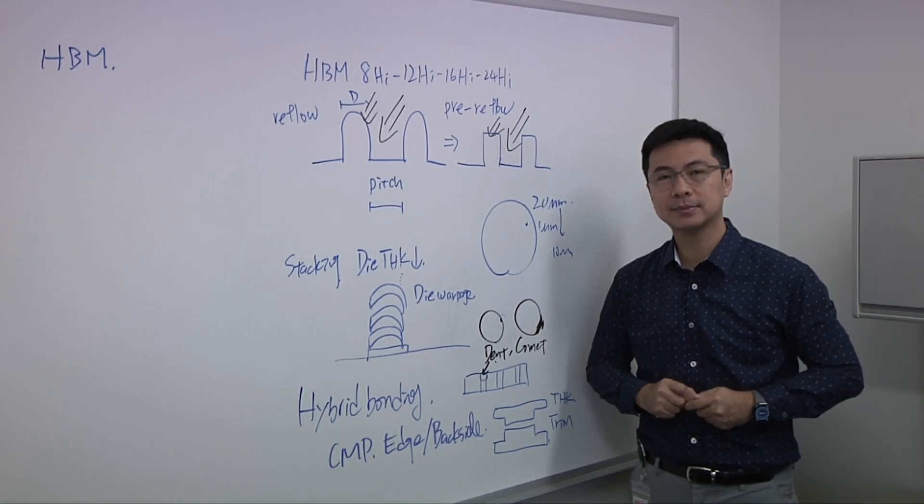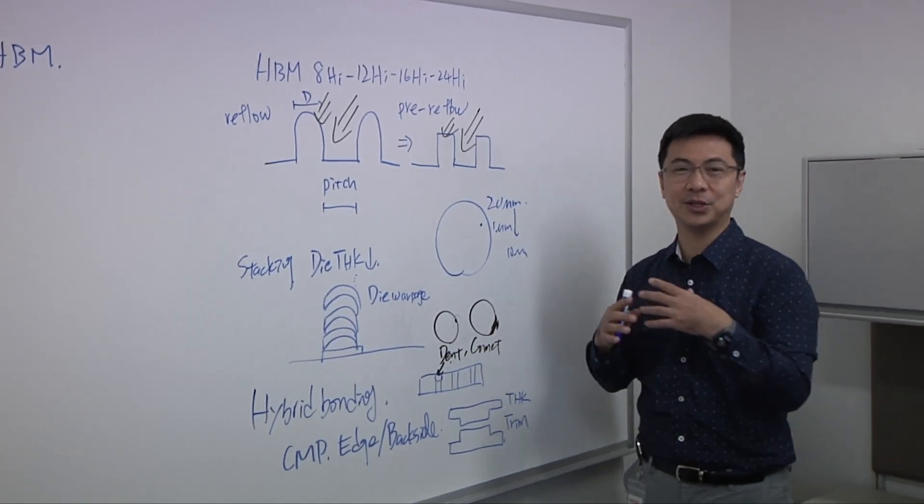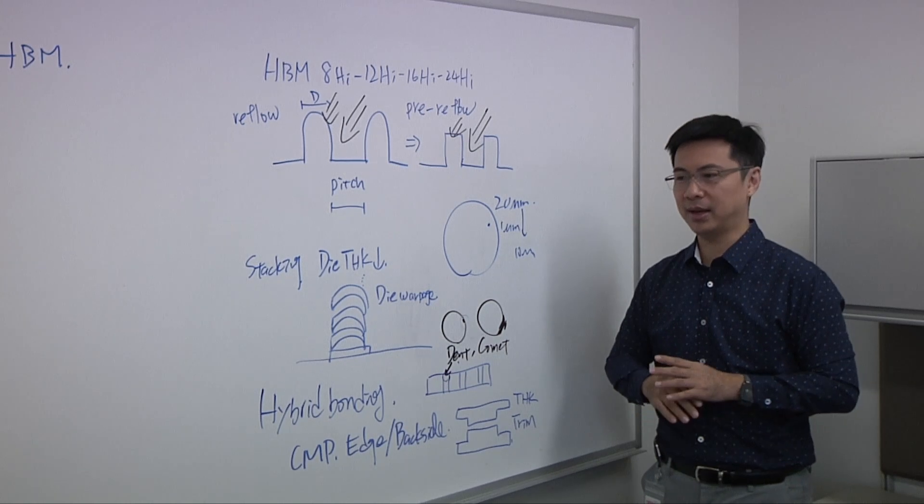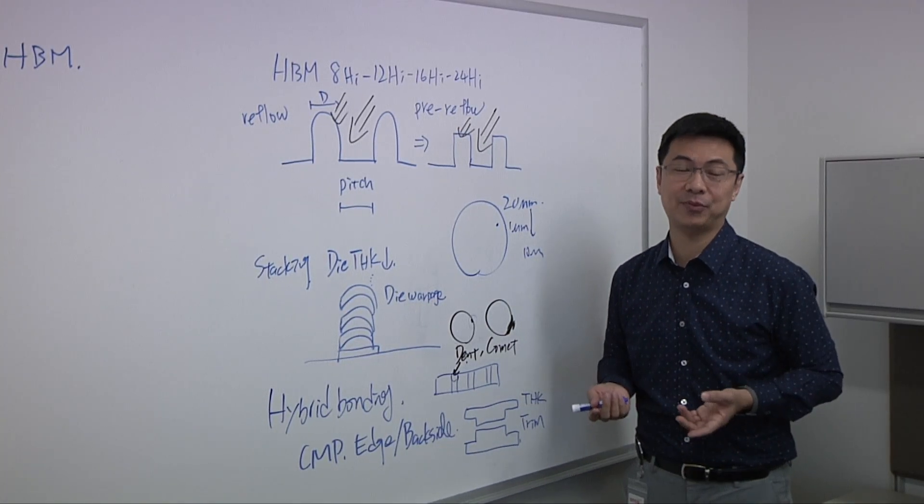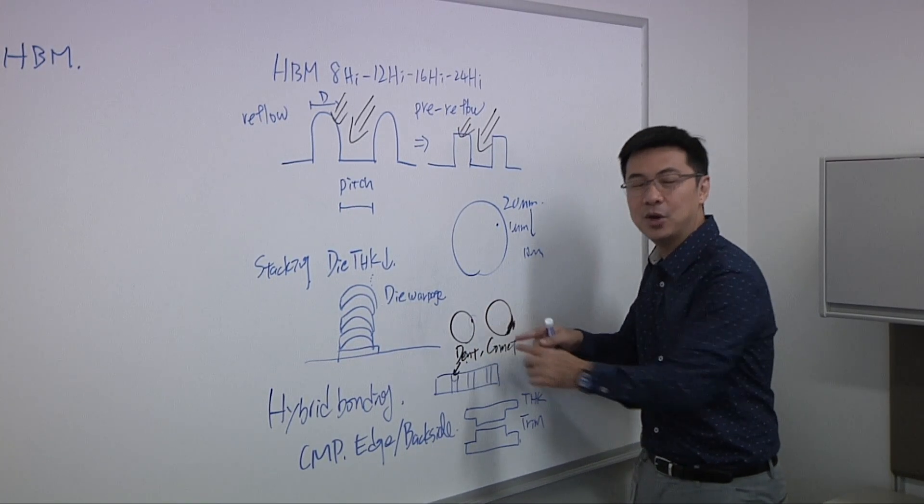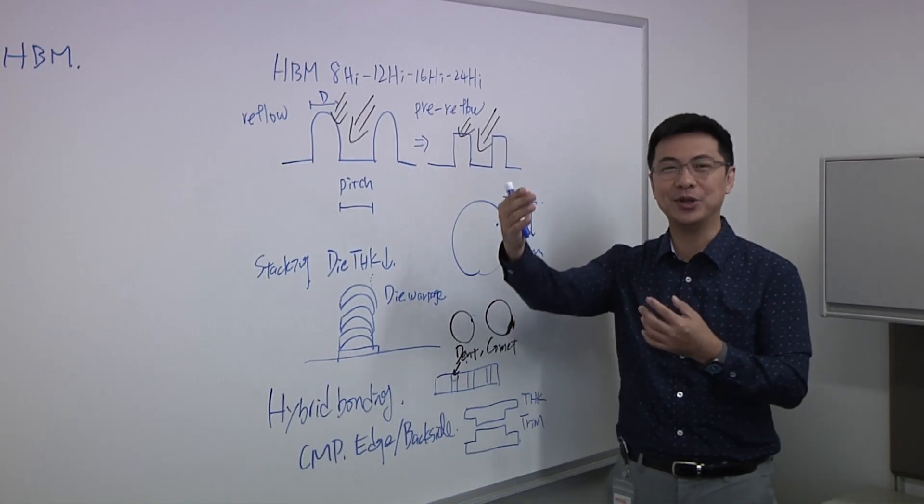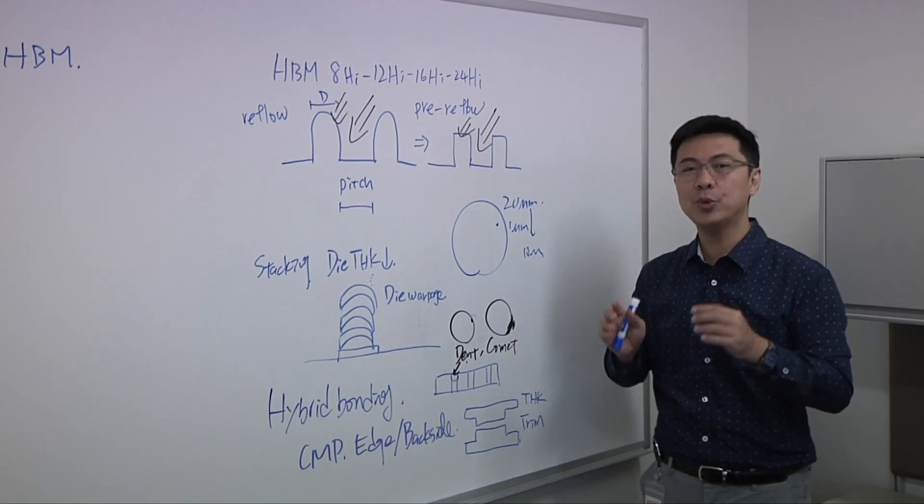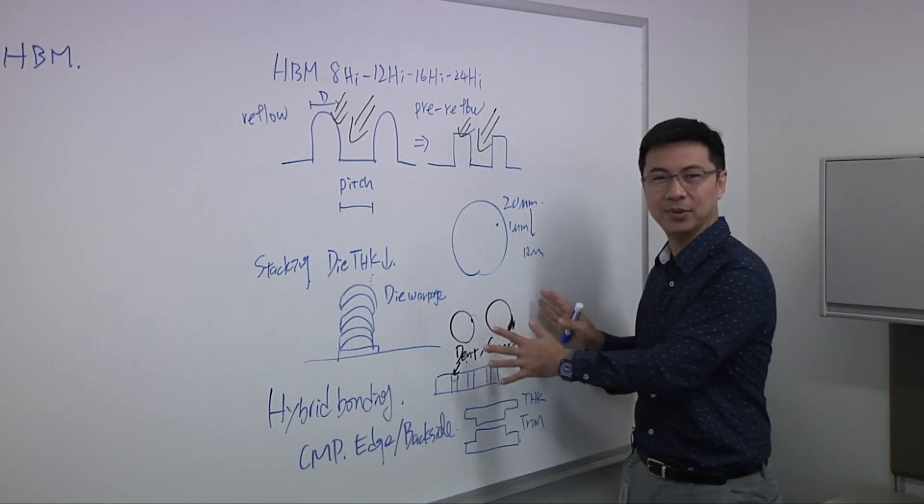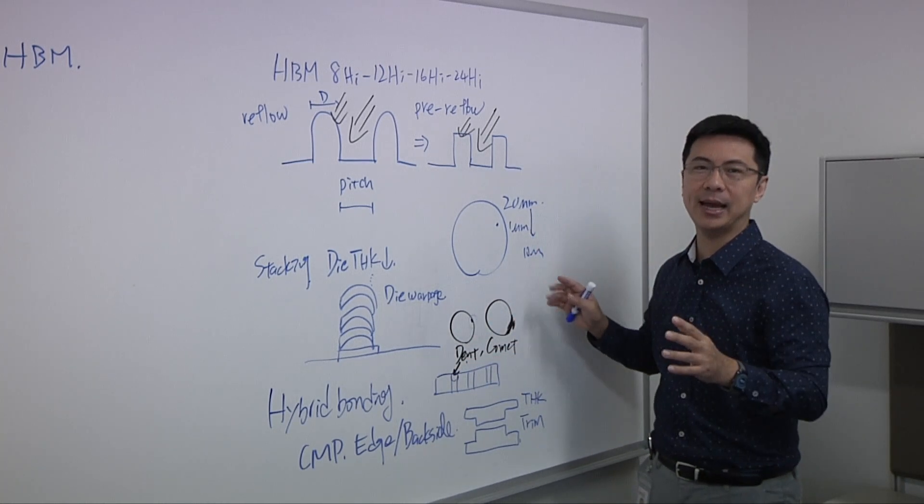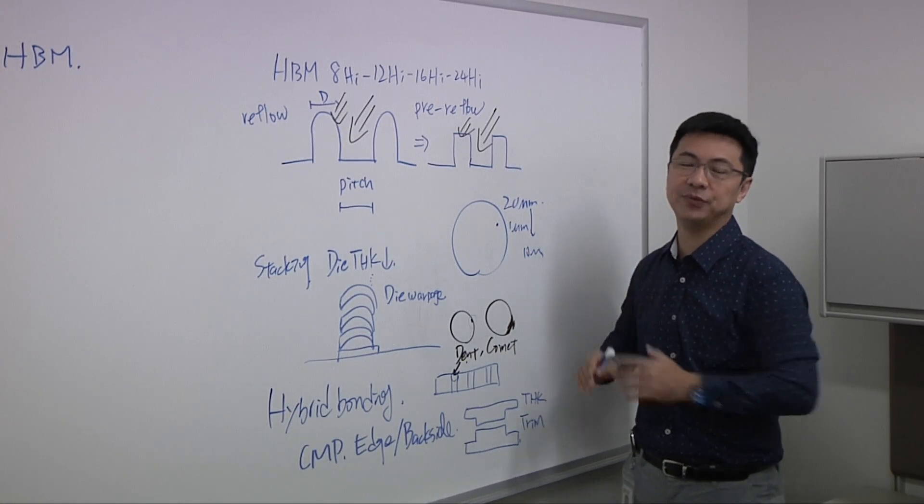So you either have to get your process absolutely right, or you need to add a lot of redundancy in here, right? That's true. So let's talk about this. Because I think, so let's go back to the defect inspection. I still remember at the beginning, we are talking about like 1,000 defects per wafer. So maybe the DOI is 100. So we just need to reduce like 10% of the nuisance defect. But right now, in order to see this kind of tiny defect, we are inspecting like 100,000 defects per wafer. Then that means the nuisance becomes 90%. So how we can reduce the redundant defect, that is the key. And also, we cannot spend too much time just on the nuisance defect, right? So that's why, back to my original statement, why we want to introduce AI to enable the next-gen AI. Because there are so many redundant data, and we need to find a way to very smartly filter that out at once. Otherwise, we will take forever to do the inspection. And that would not fit into the HBM environment for sure.